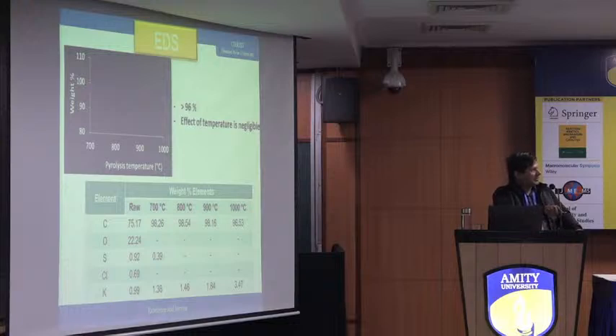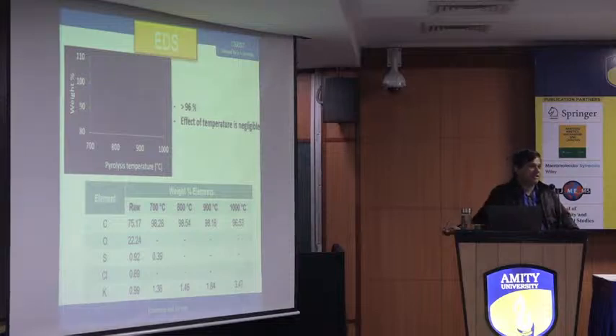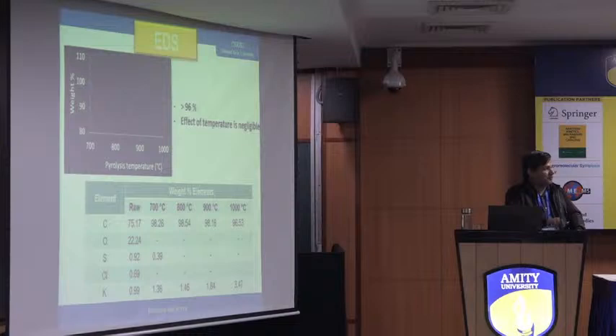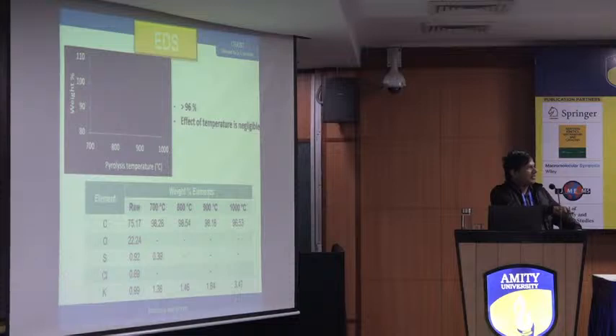You can see here, this is the raw material. But the surprising thing is when you synthesize at 700 to 1000, the carbon nanoparticle percentage is around 98.5, which is huge. People talk about 85 to 90%, but this particular material has almost 100% carbon. Why are they getting 100%? Because of the selection of the agricultural crop: the raw material itself is 75% carbon. So when you subject such raw material to pyrolysis, you get around 20-25% added, because all the lignocellulosic content will evaporate. Because of that, you end up with a very rich amount of carbon. But as an industry person, he might think that 700 is sufficient because it already has 98%.